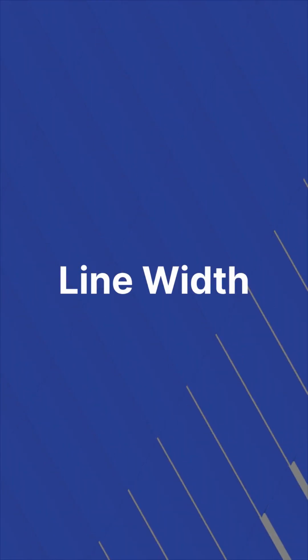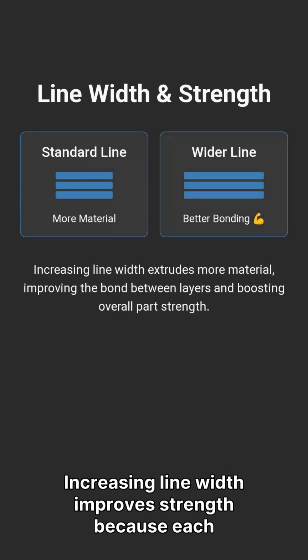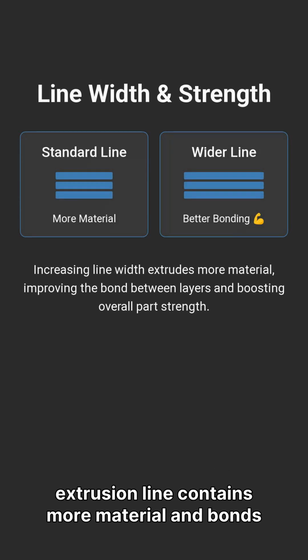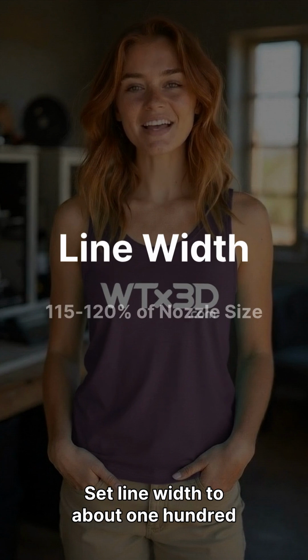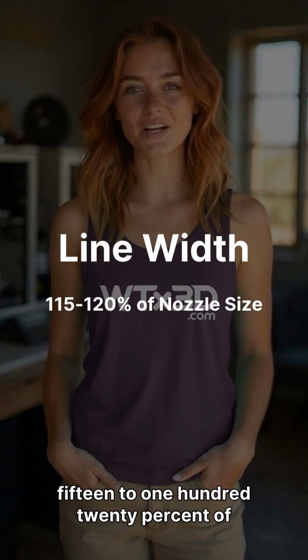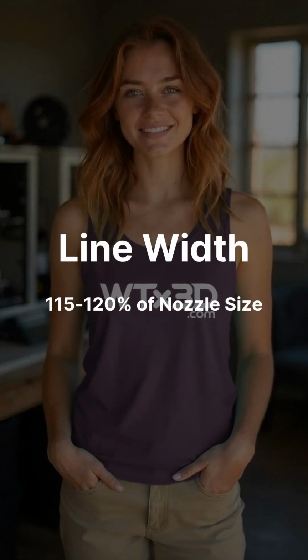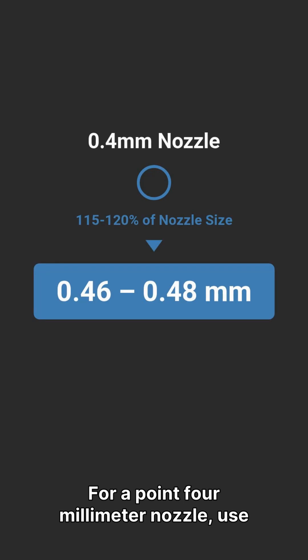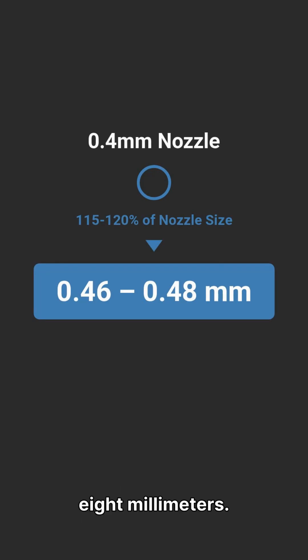Next, line width. Increasing line width improves strength because each extrusion line contains more material and bonds better. Set line width to about 115 to 120% of nozzle size. For a 0.4 millimeter nozzle, use roughly 0.46 to 0.48 millimeters.